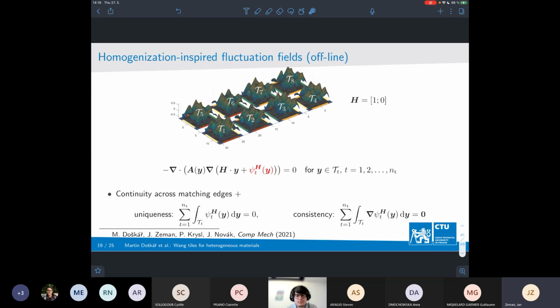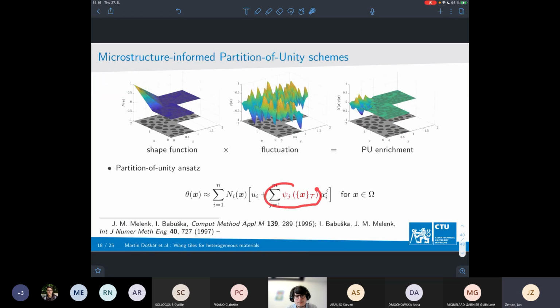So using that, actually computing that using standard finite element procedures, we can get these individual fields, which are parameterized by the affine part. So this corresponds to macroscopic gradient of a certain quantity. Here you can have a look how these look like for one example of the microstructure. If we flatten these two indices, we can actually then generate our enriching functions to the partition of unity scheme here, and then proceed standardly.